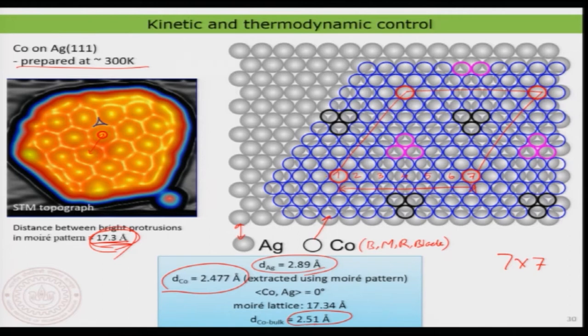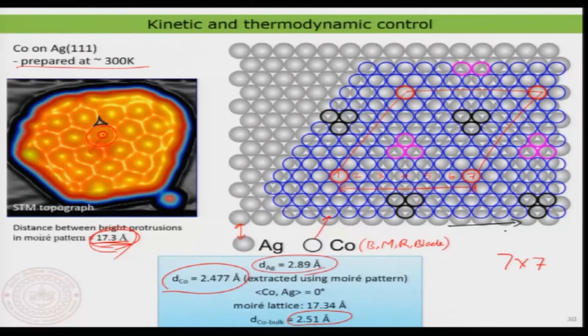Now you find that all these red spots would correspond to the red spot in the image, and the black and the magenta spots are corresponding to this point here. So there, of course, you can see the adsorption of the cobalt atom is basically on an HCP site or an FCC site, and the atoms at the red point are basically cobalt atoms adsorbing on top of an atom of the silver. Now, what I am basically doing, by slightly adjusting the cobalt lattice, keeping the surface lattice the same, is recalculating or making a model in order to satisfy the experimental parameters. Now you can see that the silver lattice and also the cobalt lattice are aligned.